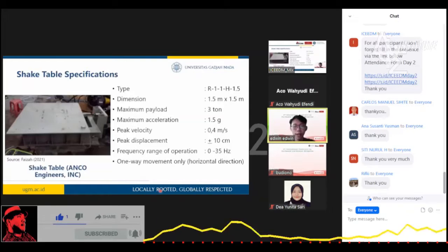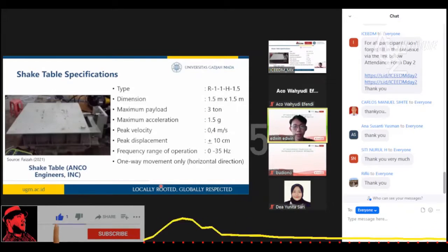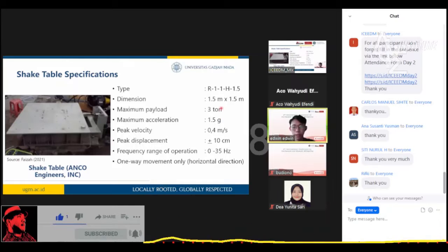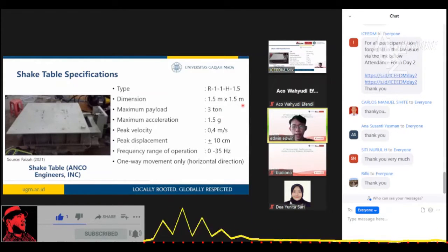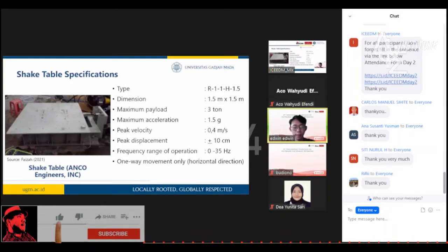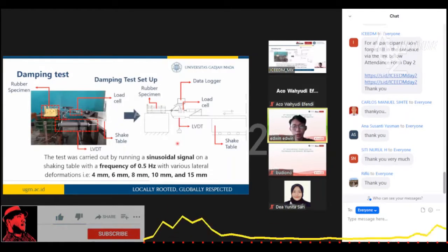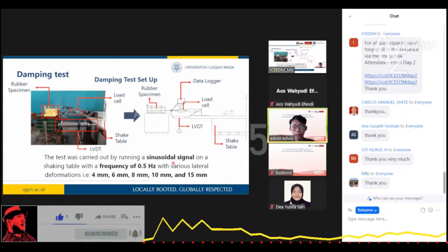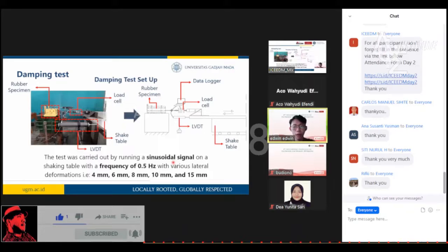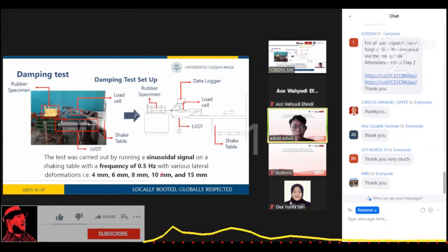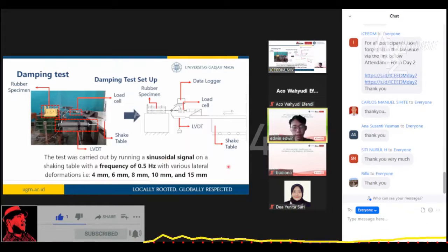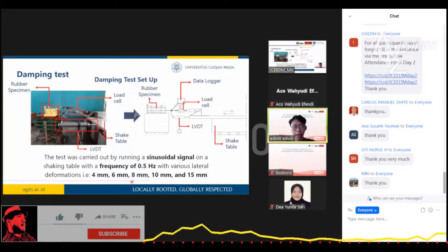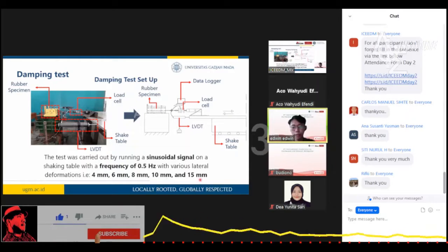The damping test was done using shake table from ANCO engineers with dimension of 1.5 meters times 1.5 meters, and the other specifications can be seen on the slide. Next, we can see the setup used for the damping test. The test was carried out by running a sinusoidal signal on the shake table with a frequency of 0.5 Hertz with various lateral deformations, 4 millimeters, 6 millimeters, 8 millimeters, 10 millimeters, and lastly 15 millimeters.